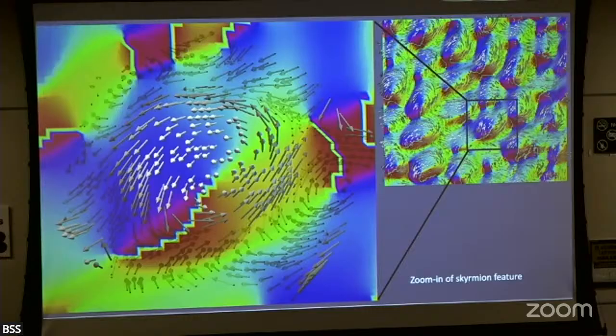It's a gadolinium iron multilayer fabricated by Eric Fullerton's group on a silicon nitride membrane. It's a dipole stabilized skyrmion sample. And we didn't care what the sample was, we just wanted to show we could image a sample with only magnetic contrast.